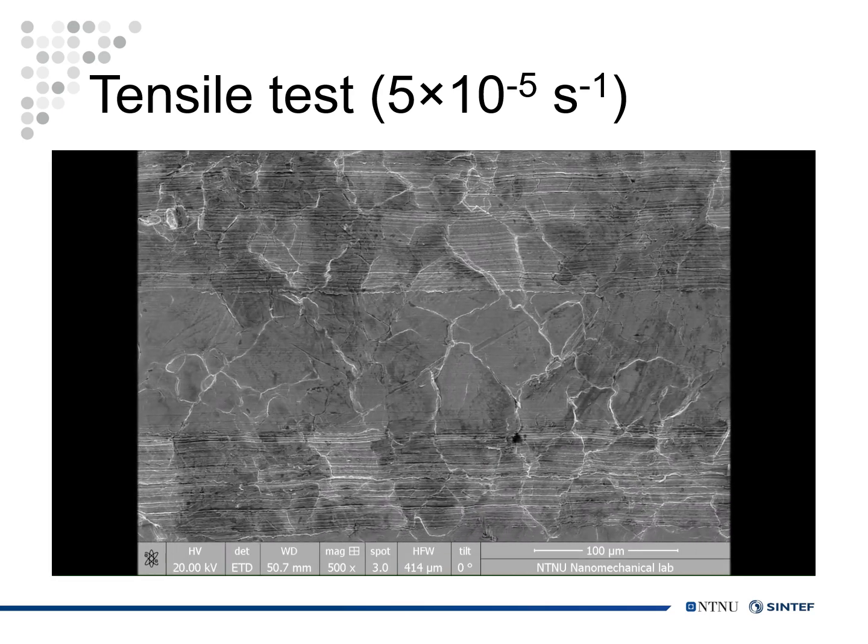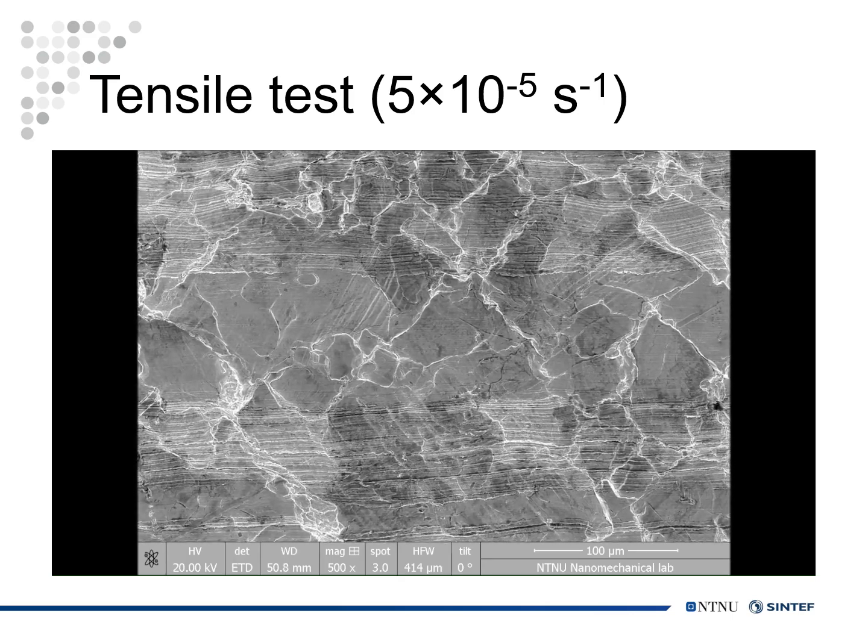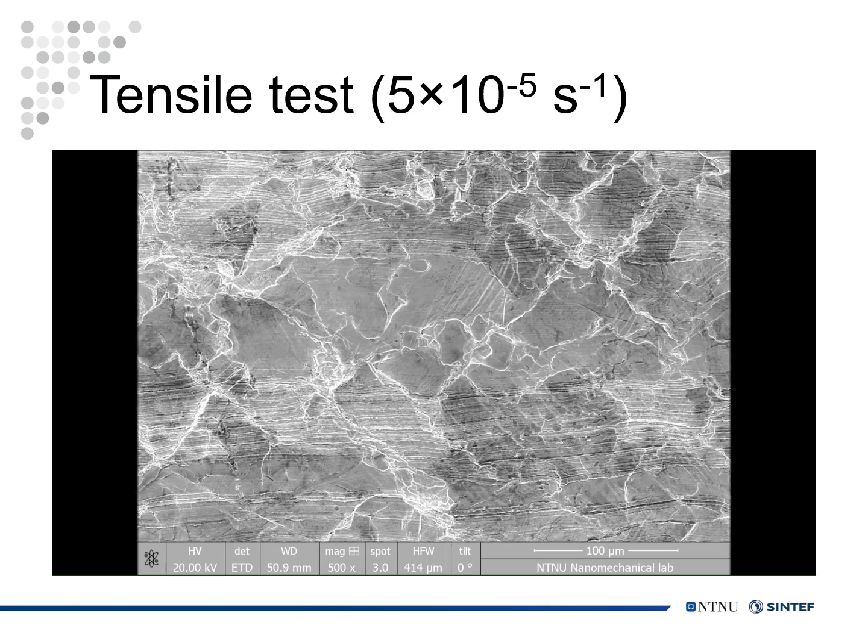After we improved the surface quality and slowed down the strain rate, this becomes more obvious. Especially here you can see the deformation was accumulated along the boundaries, and you can even find some damage initiated from the boundaries.